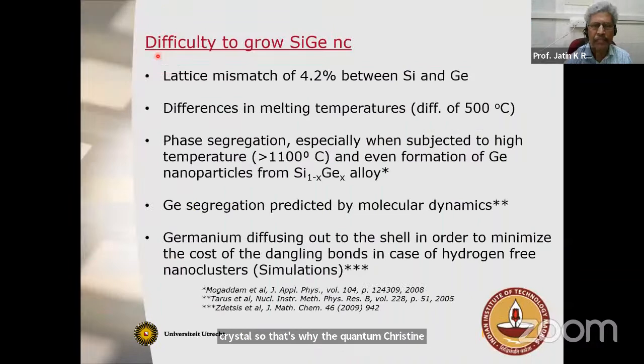But then when you start making silicon germanium quantum dots, you have a problem. Because of the lattice mismatch between silicon and germanium, it will not allow it, and they'll segregate. And there is a difference in the melting temperature of silicon and germanium, and a phase segregation takes place. These are all calculated. And then germanium tends to diffuse out of the system in order to minimize the cost of dangling bonds. The dangling bond costs a lot of energy, so it wants to save the energy. So it has normally been proposed that silicon germanium or any sort of alloy is difficult to make in the gas phase.